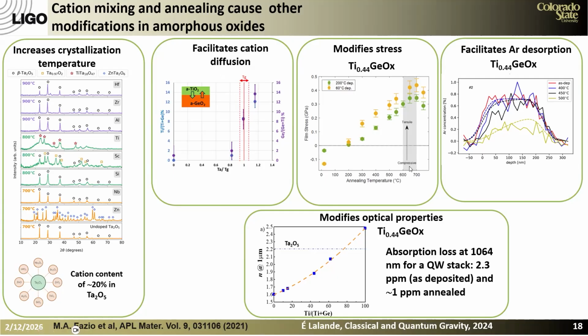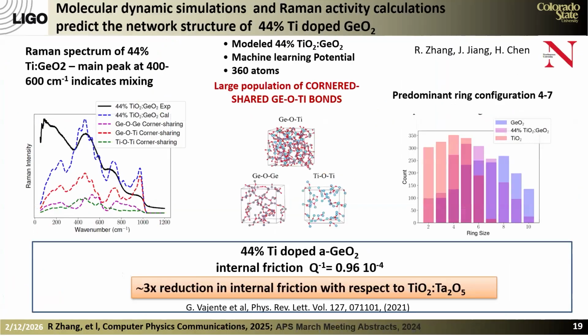Now, in Germania, we demonstrated that yes, it has these extremely low mechanical loss, but there is a challenge. Germania has a refractive index of 1.6 at 1 micron, and silica has a refractive index of 1.45. So therefore, we needed to increase the index to be able to use it in a mirror. And because of that, we started to add titanium. And we stopped at a composition of about 0.44, which was in a sense serendipitous because we didn't know that that alloy was going to give us the lowest mechanical loss.